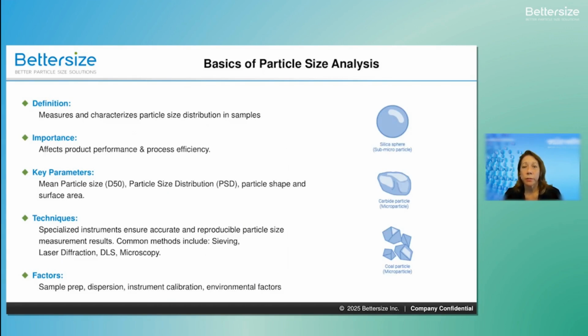So let's look at the basics of particle size and analysis. Particle size affects the packing density, the surface area, and the reaction kinetics of materials in these applications. The key parameters include the D50, which is the median particle size, meaning it represents the particle diameter, which 50% of the sample's particles are smaller and 50% are larger. So this is the key parameter for describing the particle size distribution.